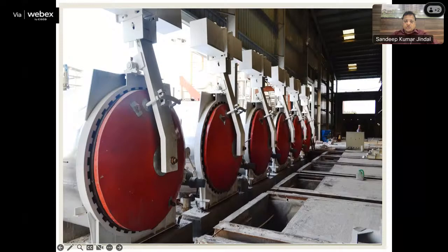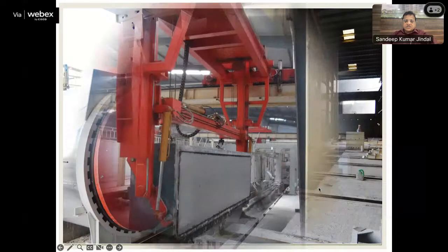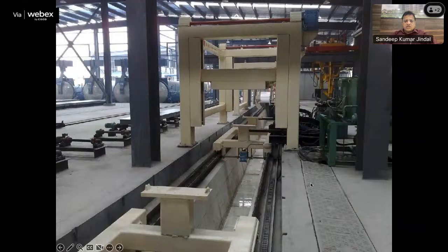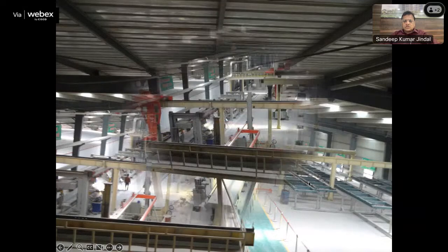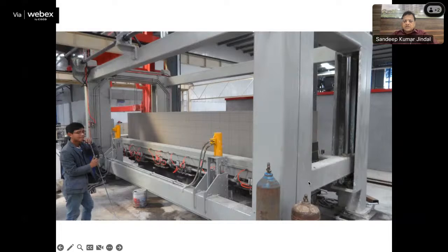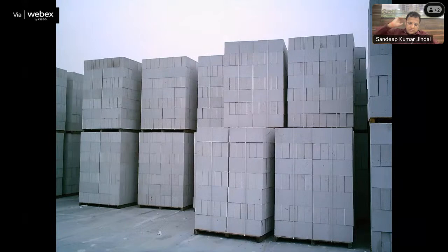So the whole curing is done in these kinds of autoclaves with high pressure and high temperature of 200 degrees centigrade and pressure ranging from 12 kgs to 14 kgs. So these are all cutting machines. So this is a very technology driven kind of project. Lot of controls, lot of things are there. It is not a normal fly ash brick manufacturing, wherein you mix it, compress it, make it and cure it in the natural process. So this is how it is being stored,